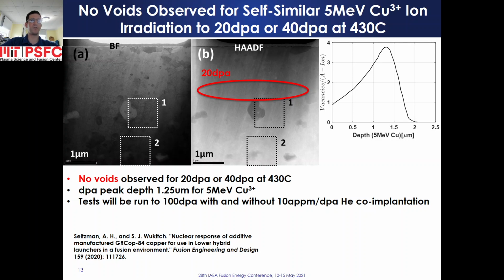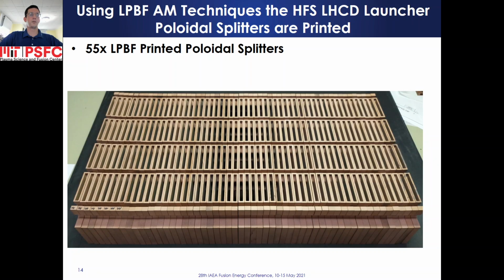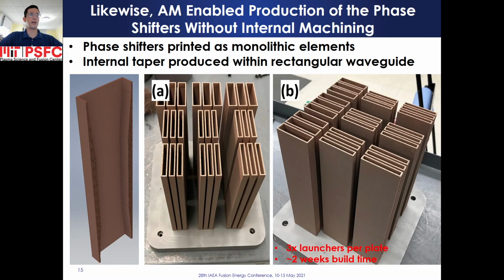compatibility of GRCop-84. Using laser powder bed fusion additive manufacturing techniques, 55 poloidal splitters for the high field side lower hybrid current drive launcher have been printed to date, eliminating conventional machining of the internal RF structure. Likewise, additive manufacturing enabled production of the internal taper within the rectangular waveguide structure of the phase shifters without internal machining. Phase shifters for 3 launchers are printed per build plate, each print taking approximately 2 weeks.